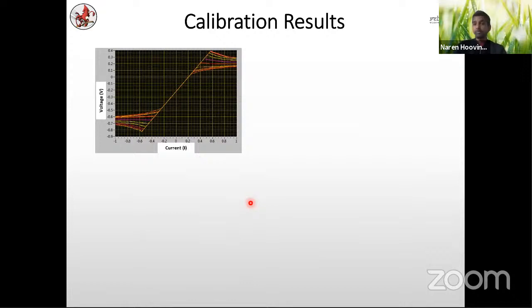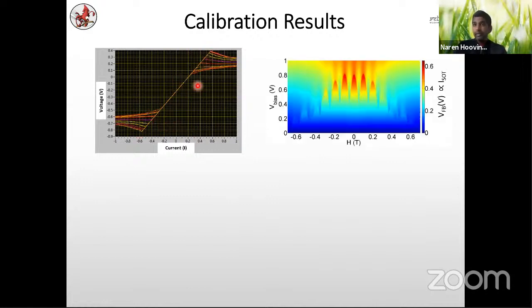And then what we measure is basically current versus voltage characteristics of this device. So we vary the current flowing through it and measure what voltage we get. So basically we should get 0 voltage until it's superconducting. And then once it crosses the superconducting threshold, there is a voltage that develops. So the curves from that circuit look something like this. And then this can be translated into a false color plot. We plot all 3 quantities in the same plot like this.